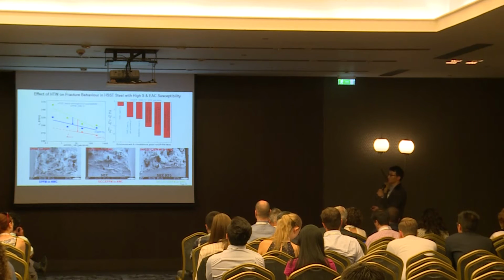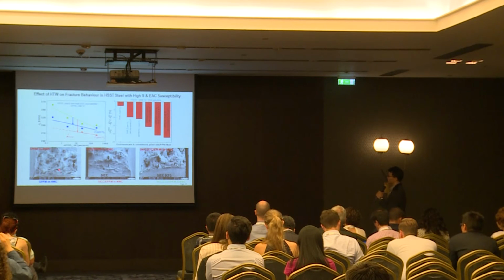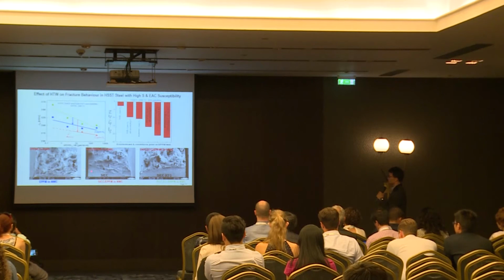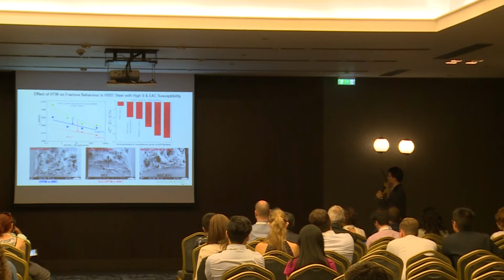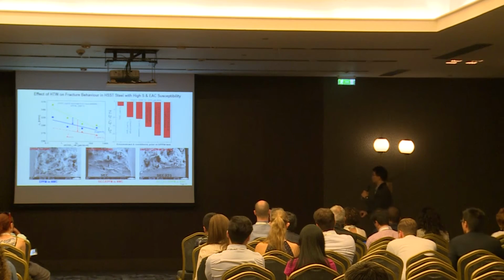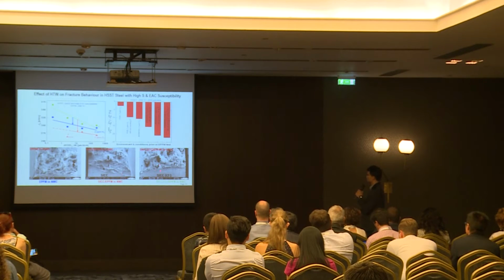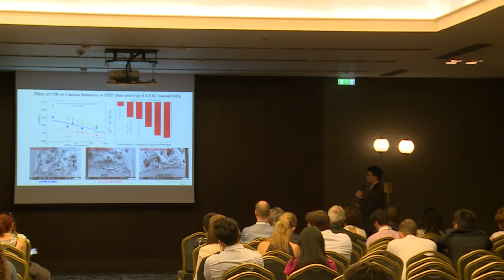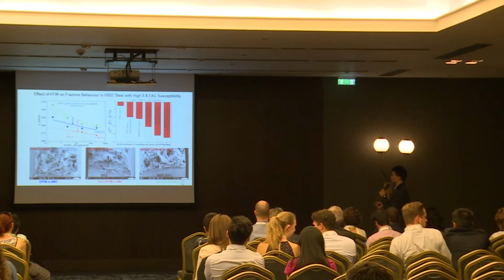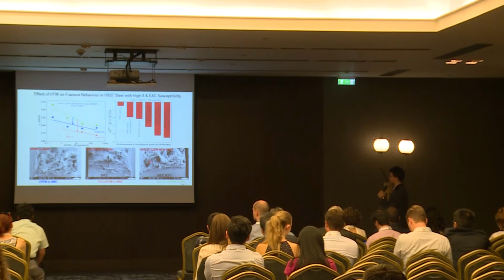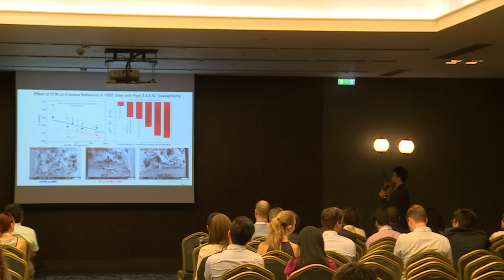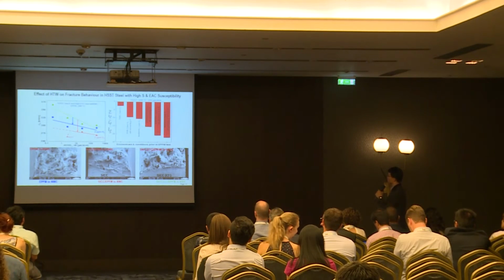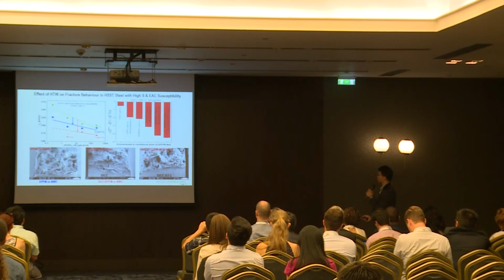If this is right, then if we can further make the crack chemistry more aggressive, then we can even observe stronger environmental degradation. To test this, in addition to the test performed in oxygenated water chemistry, we initiated the crack with subcritical strain-induced corrosion cracking before the fracture mechanics test, to make the crack chemistry even more aggressive. And in some tests, we added 50 ppb of chloride as impurity to make the crack chemistry more and more aggressive. And actually, the test results fulfilled our expectation. So we observe, with the more aggressive crack chemistry, a stepwise decrease of the crack initiation resistance, and also the area fraction of the secondary cracks and microvoids on the fracture surface increased.